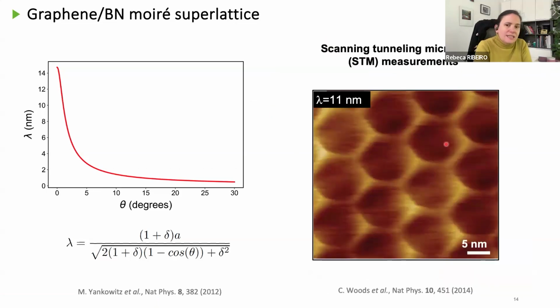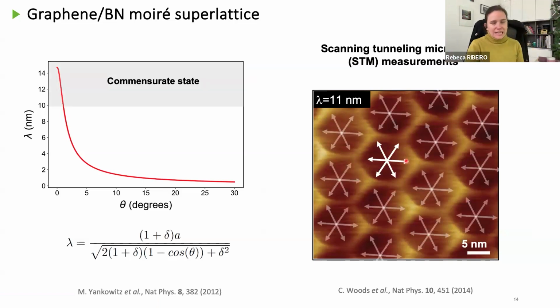And what is happening here is that inside the moiré cell, that is this one here, you will have a strain. In fact, the carbon atoms that are sitting on boron nitride will enlarge to match the lattice of boron nitride, that I told you before is 1.8% larger than graphene. This strain will propagate until it cannot hold it anymore, and then it will release it in the form of wrinkles or corrugations, for example, that you can see around here. This is what we call the commensurate state. And in fact, you might intuitively think, okay, but then it's not just the moiré, this stretching will also modify the electronic properties. And this is basically what we are gonna discuss today.